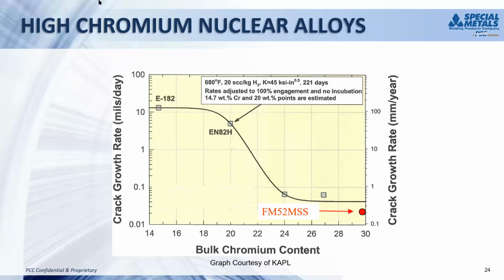So the second generation bumped up the chrome level, as you can see, to about 24 to 26%, with some of the latest alloys closer to the 30% chromium level, which basically just really minimized the crack growth from stress corrosion cracking. That was a big problem in those reactor components. Next slide.